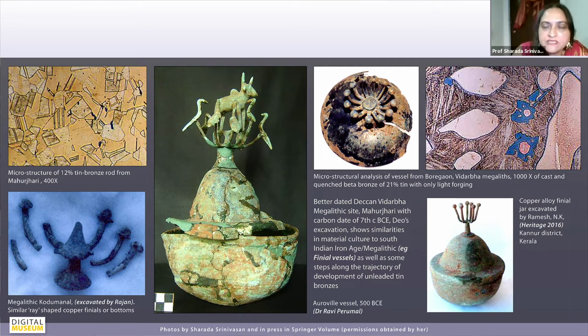And some of the other material, Adichanallur and Nilgiris, can also be dated back to the early to mid first millennium BCE. So that's not out of place. And what's also interesting is that at Mahurjari, you also find other kinds of bronze working, which are again unleaded, experimenting with unleaded tin bronze. For instance, you have a 12% tin bronze rod and so on. So you get a sense of the trajectory. And it's also very interesting, though this is one of the few vessels from Mahurjari with a finial. But again, this is very similar to what we are finding more and more from the Tamil culture, the vessels with finials.